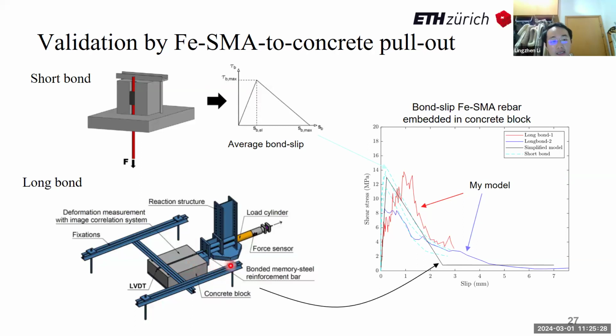First of all, he developed his numerical model with bond slip behavior as input and the force-displacement behavior as the output. During the test, he measured force-displacement curves, and he used different bond slip inputs to see which force-displacement curve could fit his experimental measurement better. In the end, he summarized such a black 3-stage bond slip curve based on trial and error simulation.